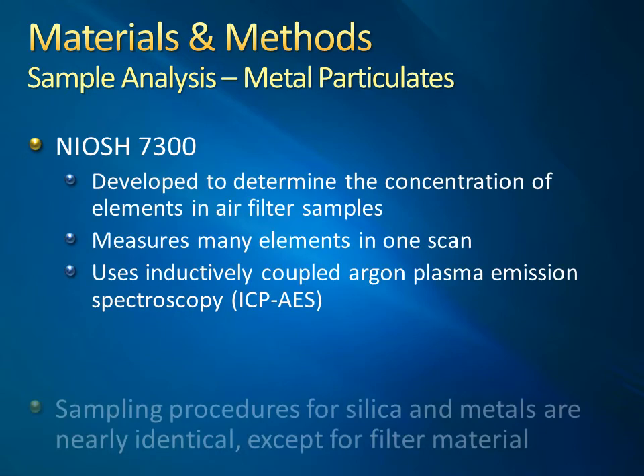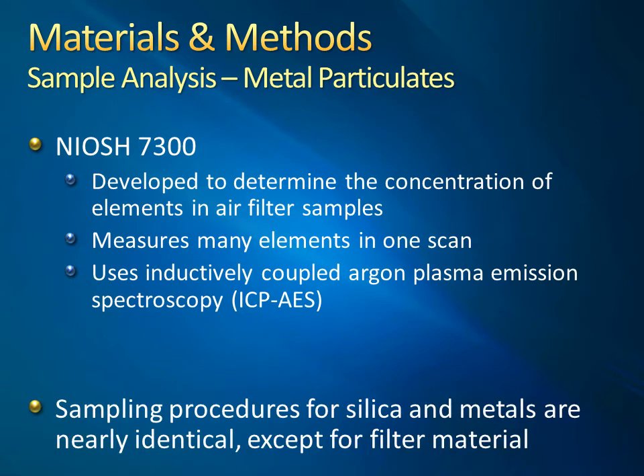The sampling of the air for aluminum fumes was determined using NIOSH 7300. This method was developed to determine the concentration of metallic elements in air filter samples by inductively coupled argon plasma atomic emission spectroscopy, ICP-AES. An ICP-AES uses inductively coupled plasma to excite the atoms of the sample, which then radiate electromagnetic radiation specific to each element's molecular characteristics.